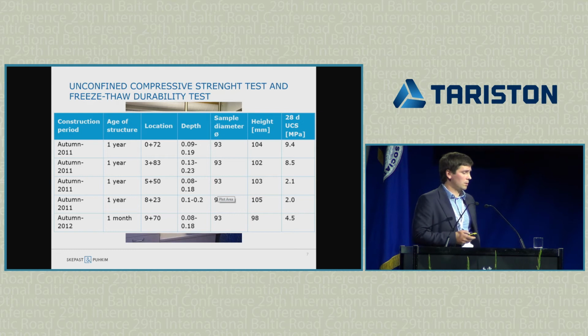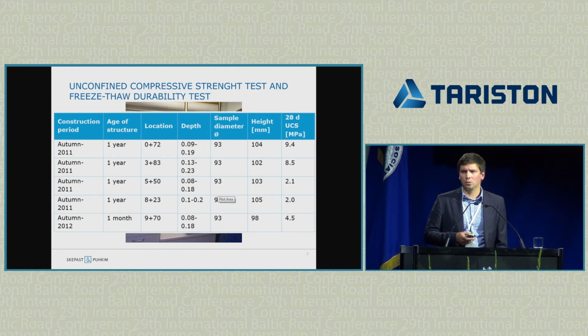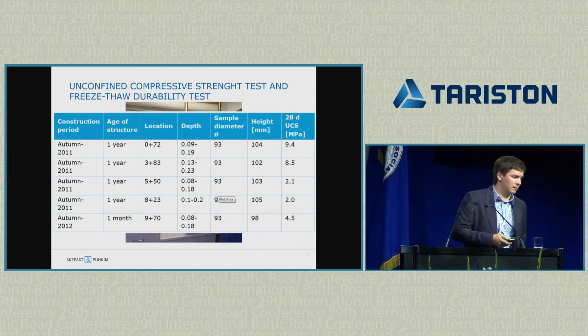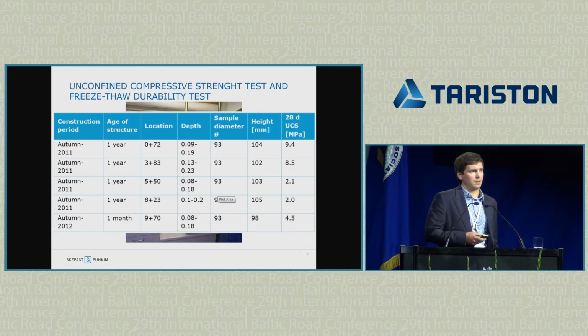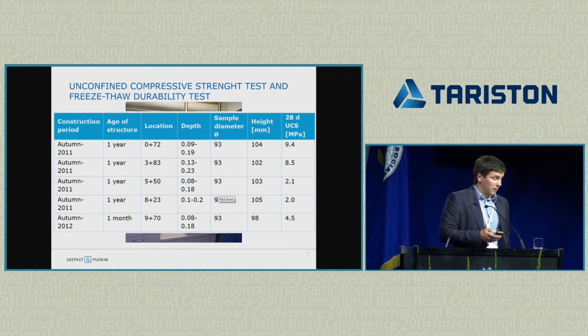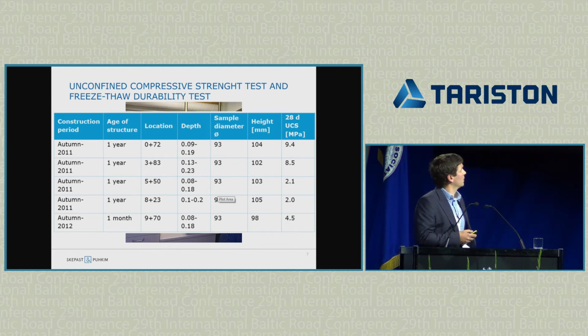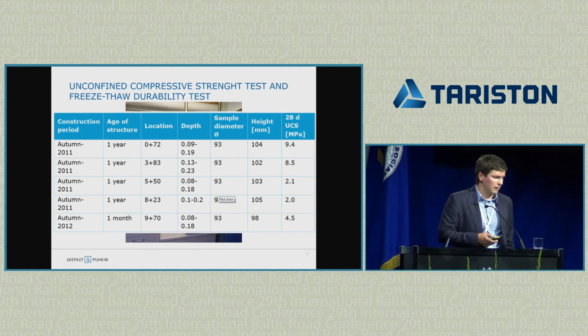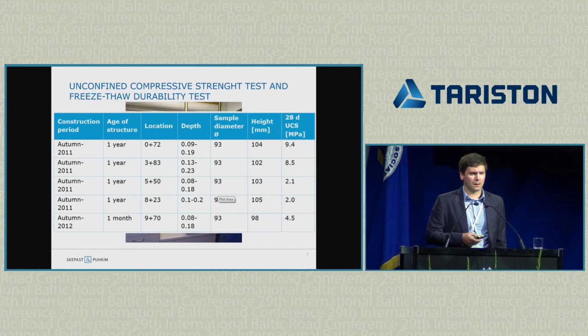And then we had this freeze-thaw durability testing, where we basically took the samples and put them to freezer, then took them out, melted them, then put them back to freezer, took them out again, and did it several times. And after that, we did this compressive strength testing again. And the idea was to check how the samples are resisting our weather conditions as we have them. And here you can see the results of the freeze-thaw testing, and the decrease of the resistance was about 15%. So this is considered as a good result.